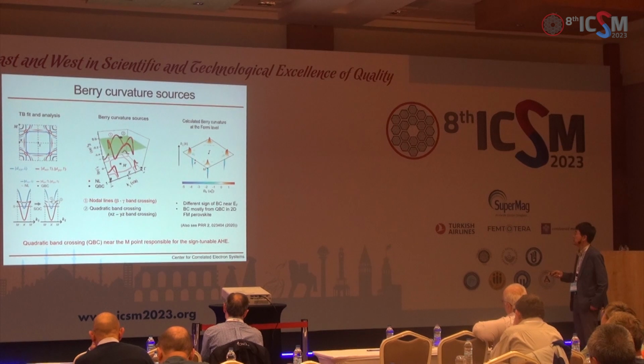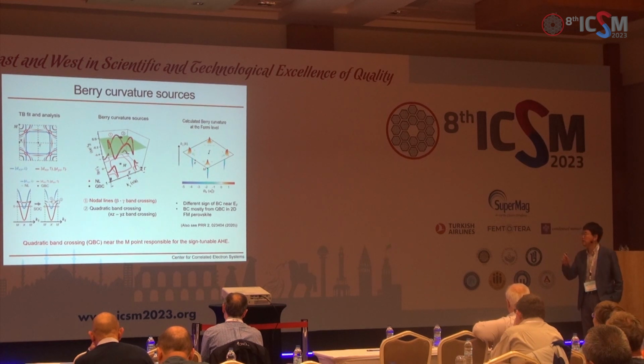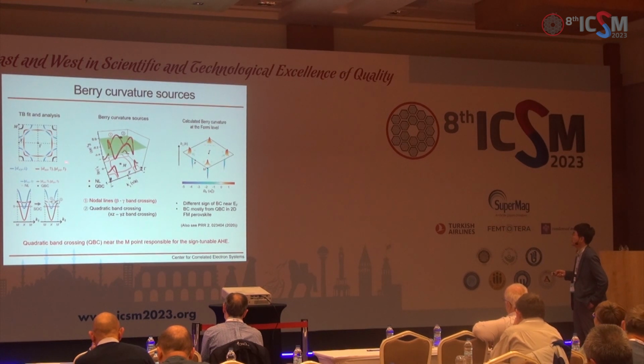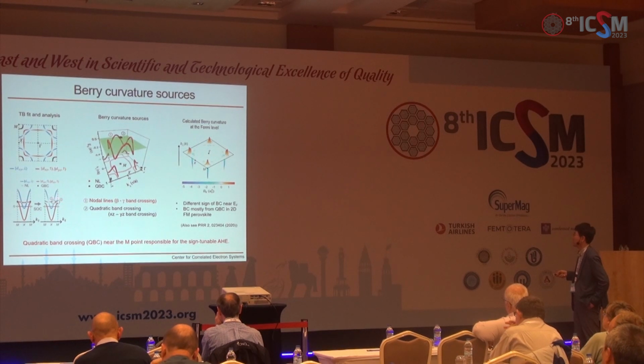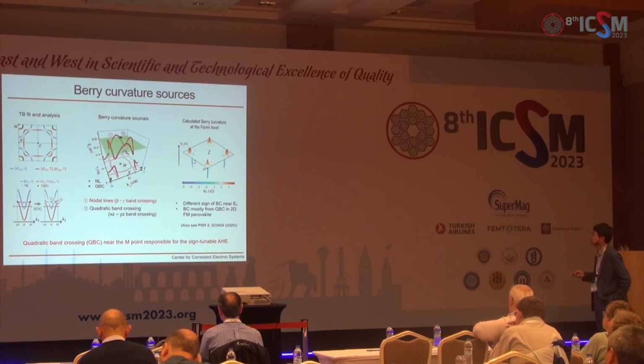Now, it turns out that only a few of these bands matter, because Berry curvature sources only near the Fermi level are important. So here are the Fermi surfaces that are important. So if I cut through one direction here, then the band structure looks like this without spin-orbit coupling. Now here we have dxy minority spin and yz, zx majority spin. With the spin-orbit coupling, they hybridize and open up a gap, and they become Berry curvature sources.